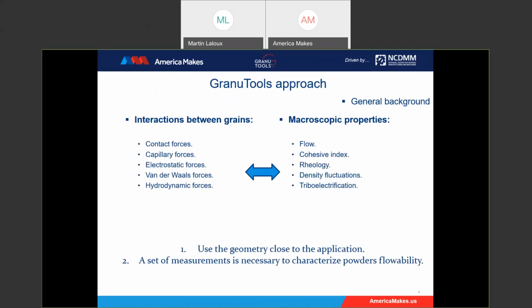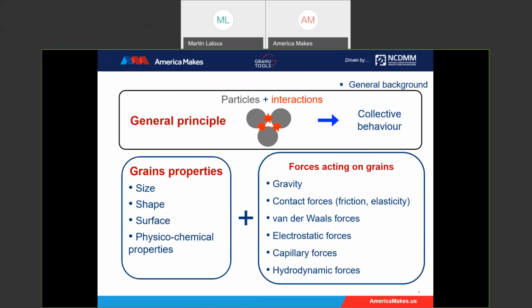We studied the macroscopic properties of a powder, so the cohesive index, the density fluctuation, triboelectricity, and we relate those macroscopic properties to the interaction between the grains, so the contact forces, capillary bridges, van der Waals, and so on. As I said, we use a geometry close to the application, here the powder bed fusion. To summarize again, we studied the collective behavior and the interaction between the particles, so the forces acting on the grains: contact forces, van der Waals, capillary, electrostatic, and so on. And we relate those properties to the microscopic properties, so the PSD, shape, physico-chemical properties, and so on.